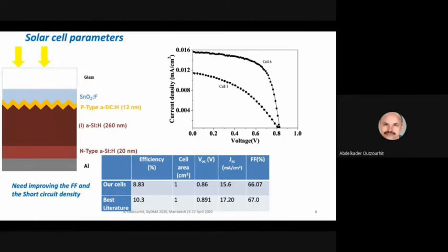Just for comparison, I also included in this table the best efficiency cells obtained in the literature in this family of solar cells, and the record efficiency in this family of cells is about 10.3%. As you can see, we are not that far. The difference is only about 1.2%. Of course, this is for a cell area of 1 square centimeter, and the open circuit voltage is also not that far from our value. However, the short circuit current of our cell is a little bit small, and the fill factor of our cell is also a bit smaller.